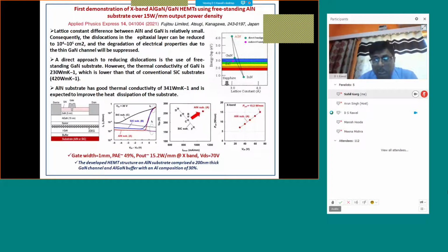So the growth defects will be minimized, and at the same time aluminum nitride has good thermal conductivity, although not equal to silicon carbide, but because of better growth parameters, because of better lattice match, the performance of these devices is expected to be very good at high frequencies. And this is the recent report of this year only, and Fujitsu has reported 15 watt per mm device at X band on aluminum nitride substrate.